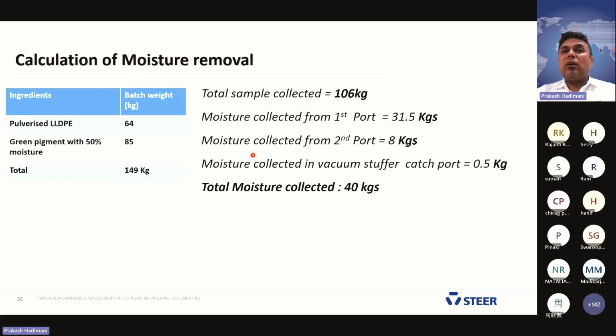In the second port, 8 kg of moisture water can be collected. And finally, the traces of volatiles have been removed through the vacuum stuffer, 0.5 kg. And water removal is almost 40 kg from the system.